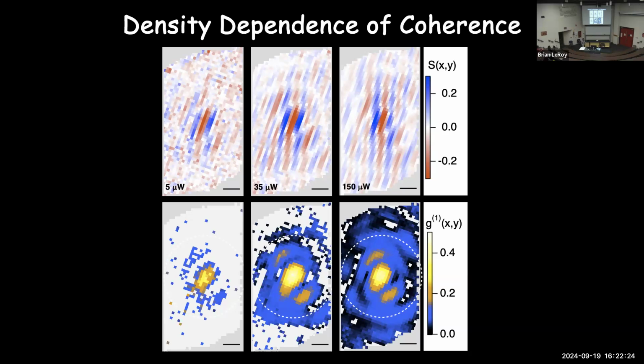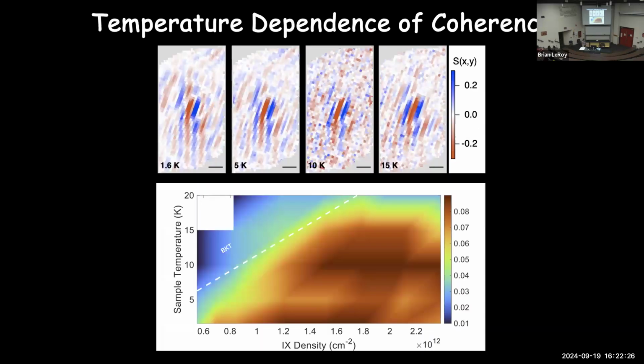The last check I can do with this is what happens as I change the temperature of the system. So as I warm the temperature up, I expect that this superfluid state would melt. And that's exactly what I see here. As I go from 1.6 Kelvin, as I increase to 15 Kelvin, I had fringes everywhere here. And now the fringes become more localized here. And there's this kind of transition here with temperature and density, which agrees quite well with the expected transition temperature there.